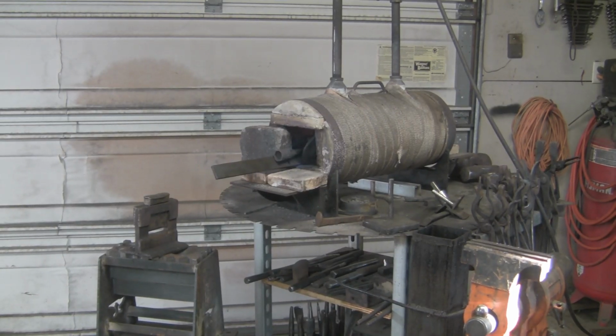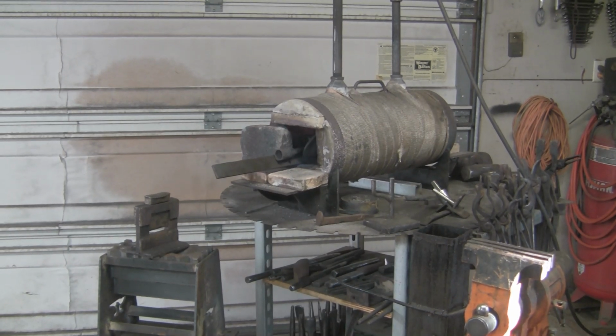So it's actually the next day, and got the clay on the blade. I actually cured it at 200 degrees and 210 degrees in the oven for quite a while yesterday. I let it dry overnight. The blade is actually in the oven right now. I have it preheating. I have the oven set up to 400 degrees. I want to kind of get the blade hot before I start the quench.